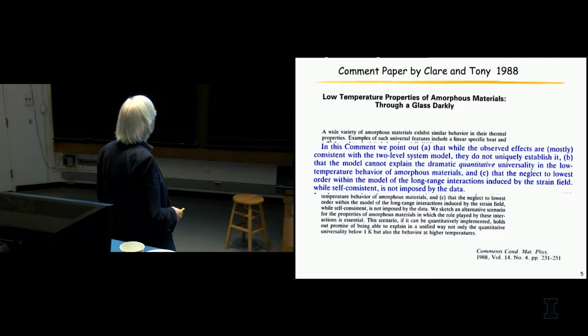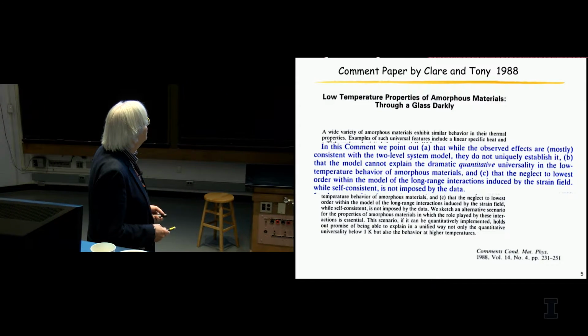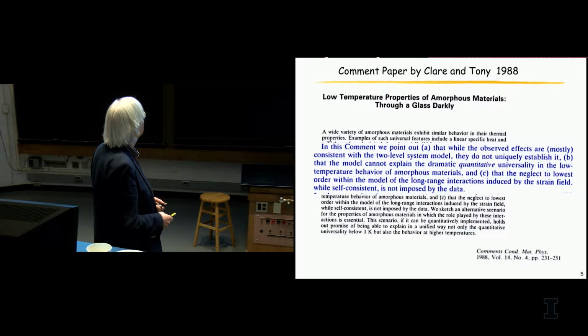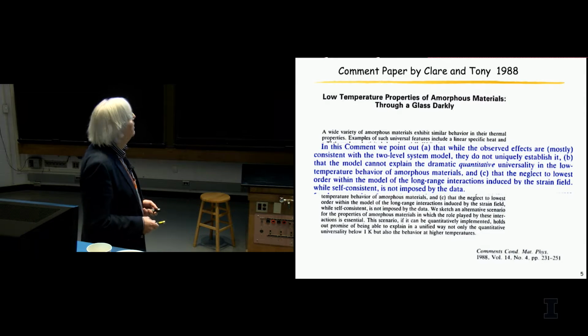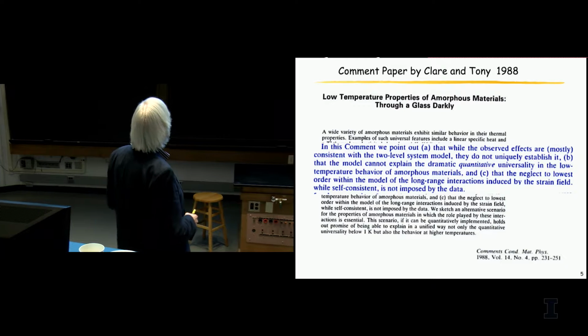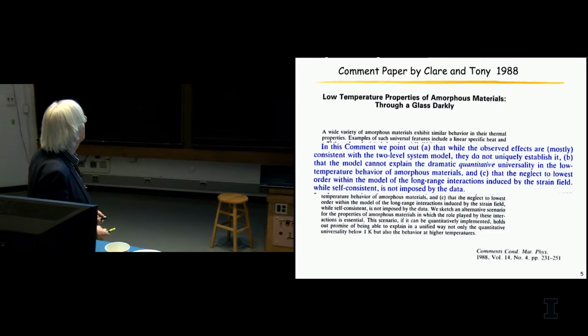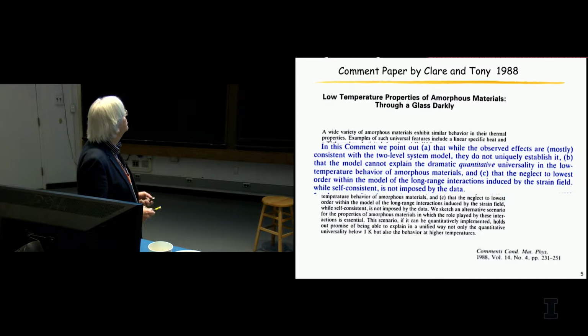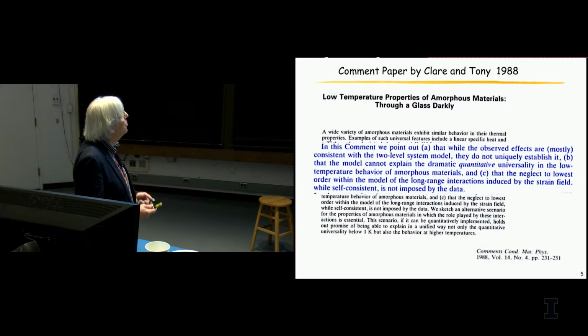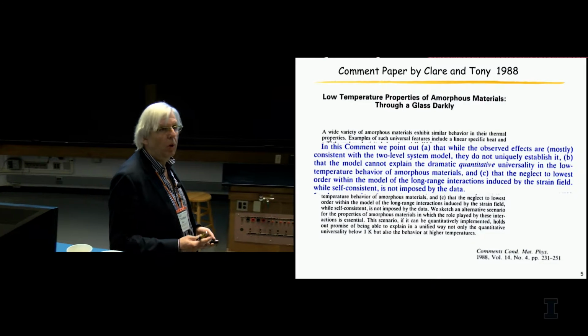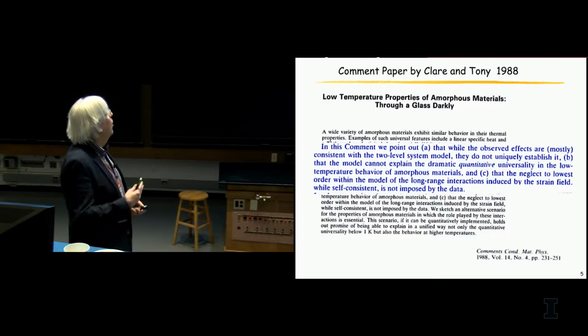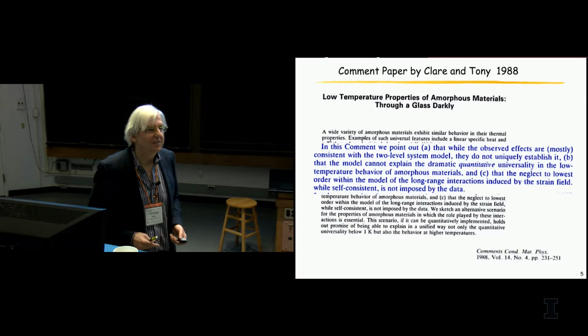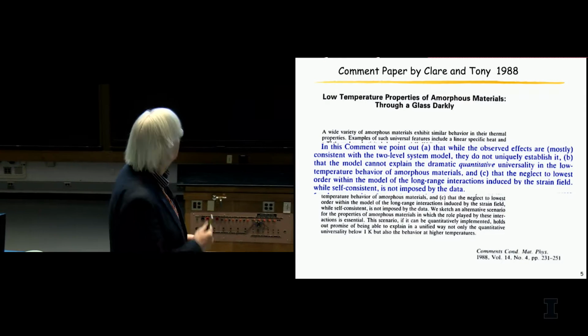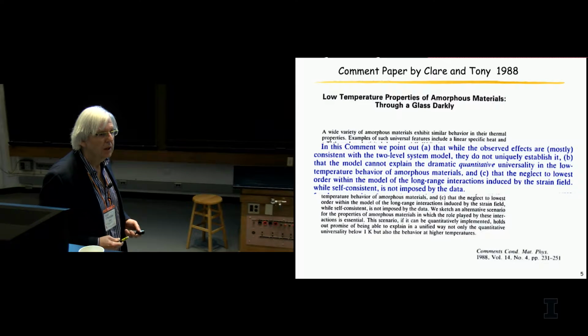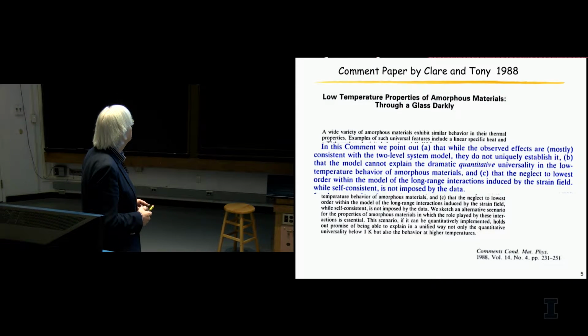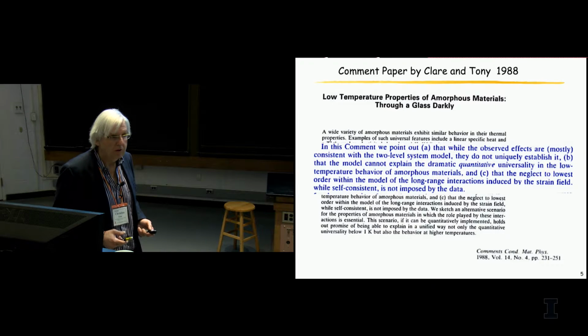B, that the model cannot explain the dramatic quantitative universality of the low-temperature behavior of amorphous materials. And C, that the neglect, at lowest order within the model, of the long-range interaction induced by the strain field, while self-consistent, is not imposed by the data. Very important questions, and of the contents of the paper, Claire will talk a little bit later on, but it generated a lot of interest, and other people tried to do experimental work along those lines.